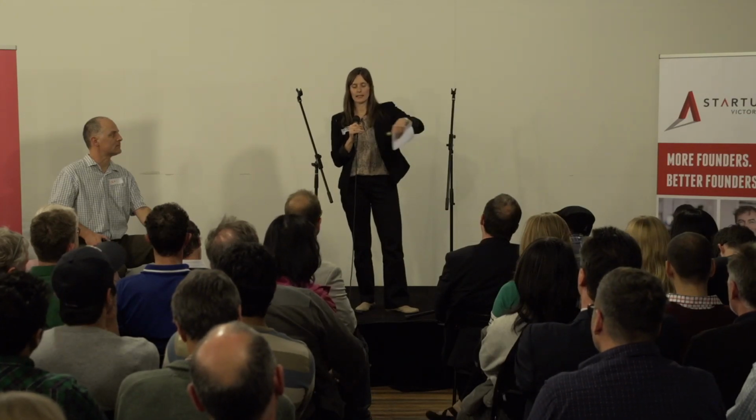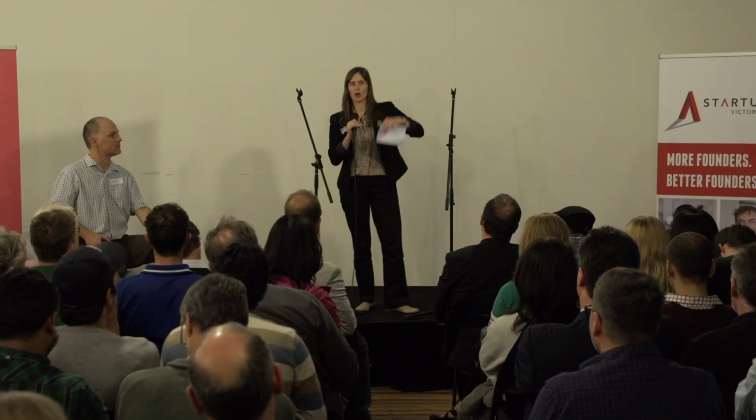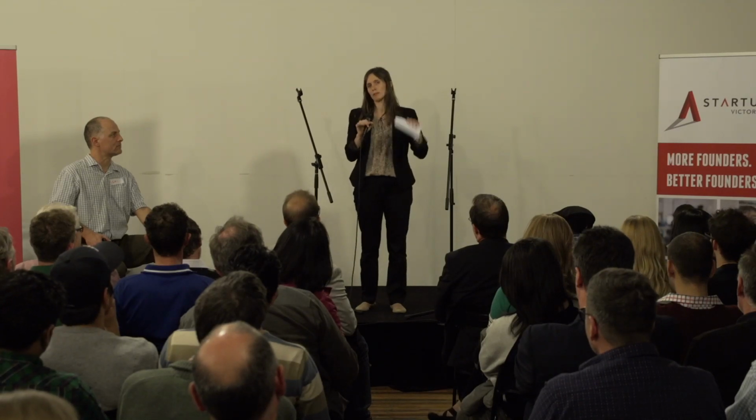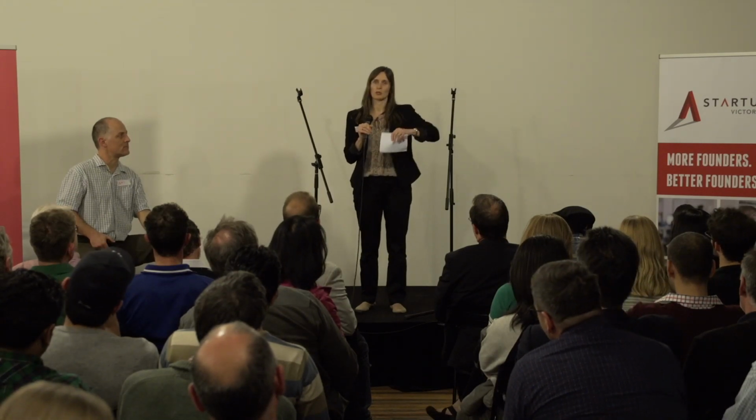It's a bit of a yes and no answer. We can basically design or maintain operating conditions to optimise a part for certain qualities and properties. As far as comparison to wrought, we get basically static and dynamic properties roughly the same as wrought. It's probably a few percent off though, so it's probably better in applications where you've got a specific property in mind. You can design it for that property. And the other thing is that when compared to wrought and welds, a welded part has a lot of variation across the part in its properties, whereas 3D printed is very uniform. If you know what you want, you can get it.